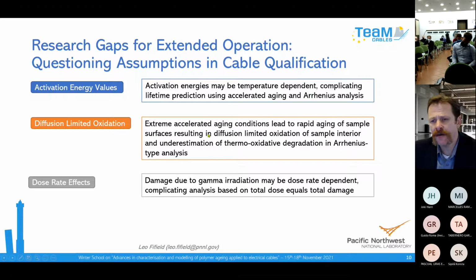Another knowledge gap we call DLO, or diffusion limited oxidation. This came about because it was observed that if you age a polymer very rapidly, such as at a high temperature, many of these polymer insulations are rated at maybe 90 degrees Celsius. But if you put that in the oven to try to make it age quickly at 165, 180 C, what happens is the exterior of the material ages very rapidly, and that aged crust forms on the material and prevents oxygen from penetrating into the interior of the polymer sample, limiting that diffusion of oxygen in. And if your major reaction is the oxidation of the organic polymer, then the aging occurs in a different way than it would over a long time at a more mild condition.